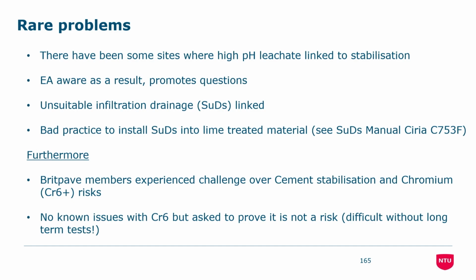Essentially, where this is developed is that unsuitable drainage has been installed into our lime-treated material, so SuDS-type drainage that actively promotes permeation of surface water into the fill, and then also out and through, and then into a watercourse. You shouldn't do that, by the way, because it's generally not a good thing to direct water into an earthwork, as it's not going to do it any favours in terms of its engineering properties. But it also specifically says don't do that in the SuDS manual, the CIRIA guide for that. It specifically says do not install infiltration drainage into cement-treated material. So it's not a good idea, but it happens.